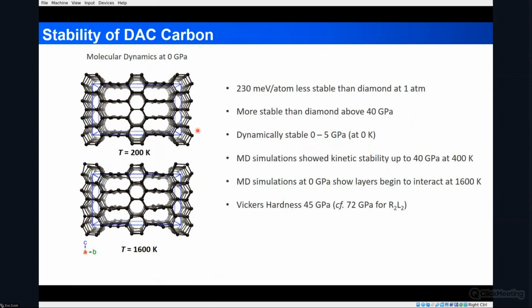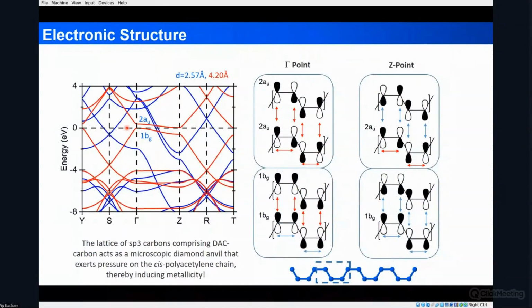And one can do molecular dynamics trajectories to study the kinetic stability and look at phonon stability and so on. And we do find that these could potentially be made at mild pressures. But what is interesting is to note the electronic structure. So if you take these carbon chains and pull them apart, what you are going to see is that this is a nice insulator. But if you squeeze them together, at the gamma point you actually get a large overlap of these p orbitals of the neighboring chains. And this is an anti-bonding type situation, so you end up raising the energy of these two bands. At the Z point, because you have this bonding type situation, you end up lowering the energy of these two bands. And because of that, this kind of pressure induces metallization.